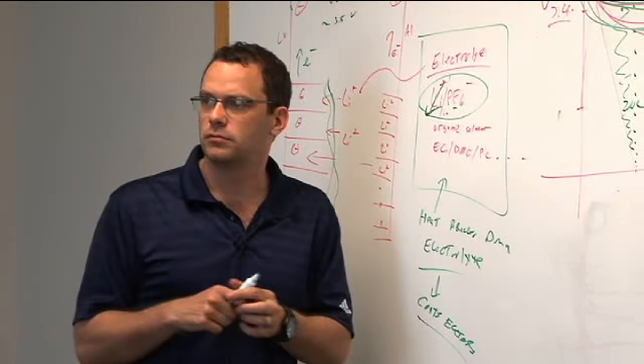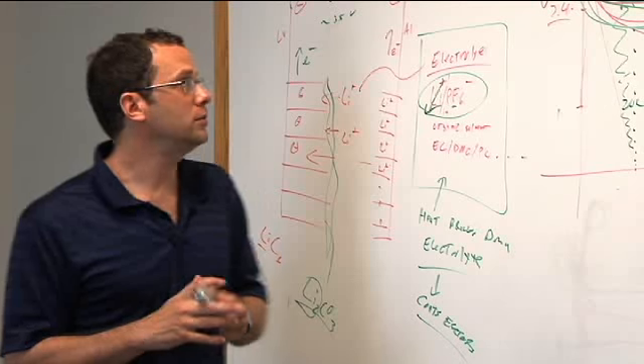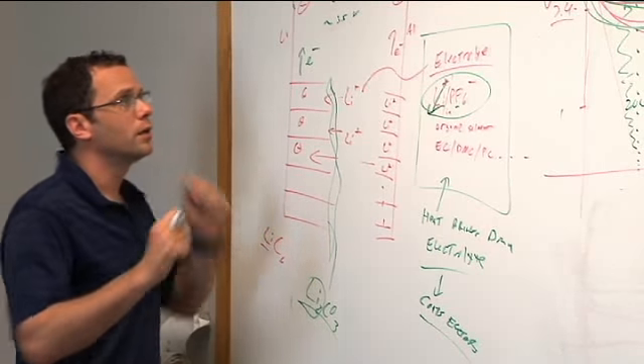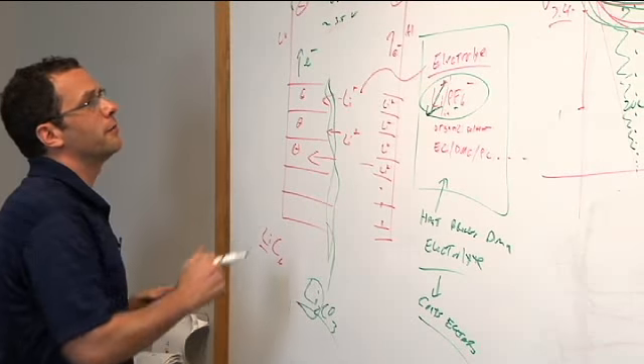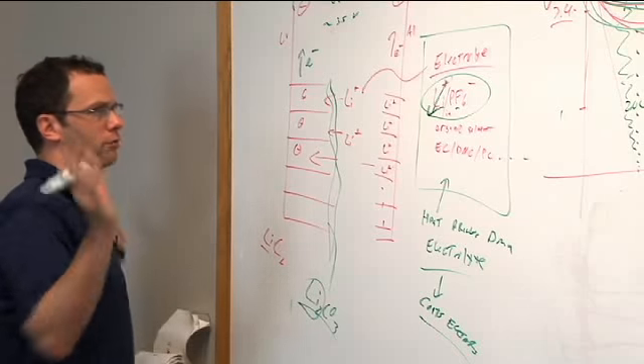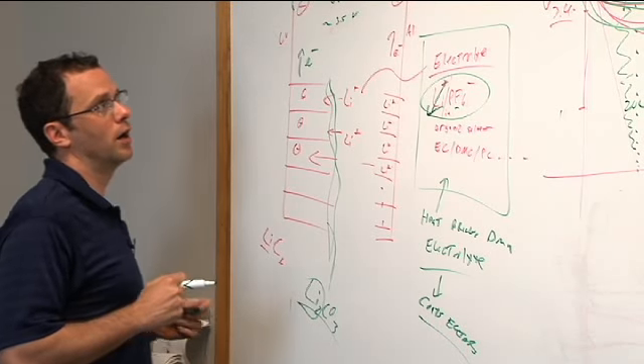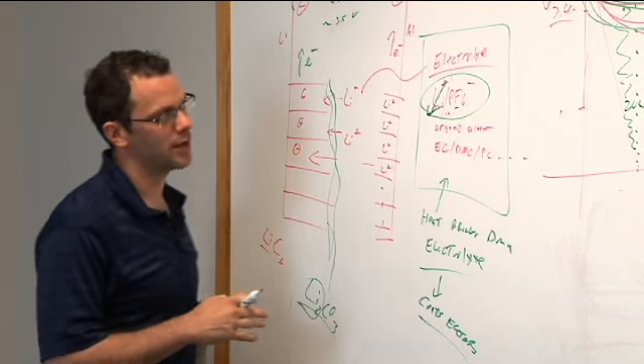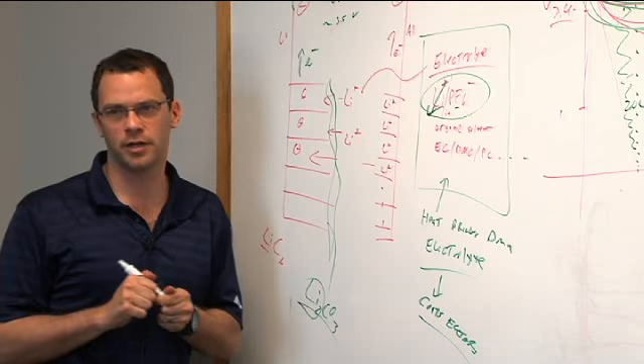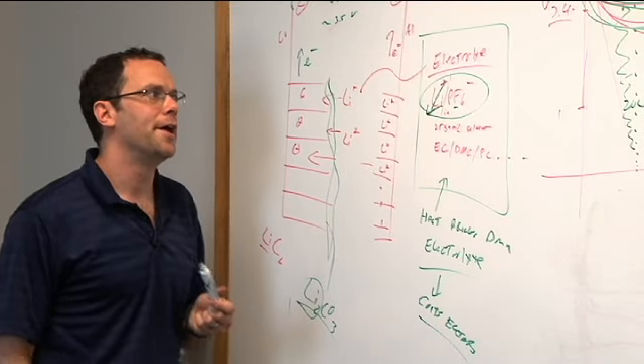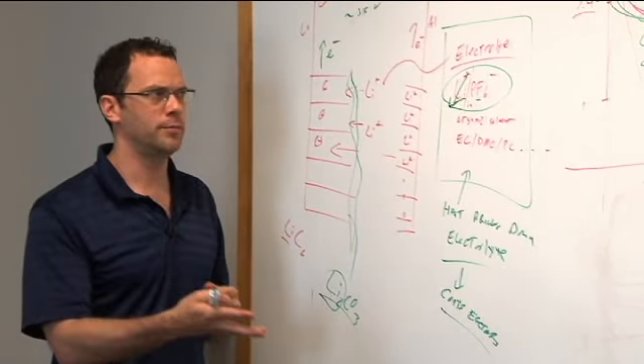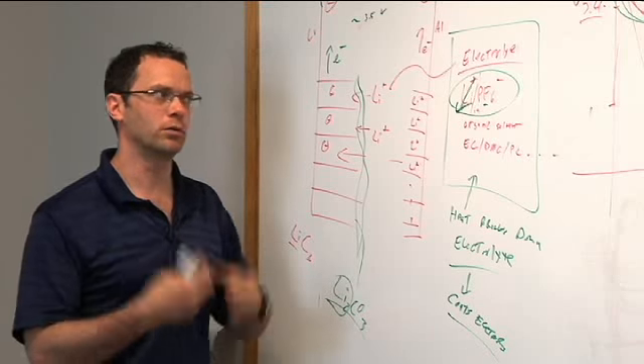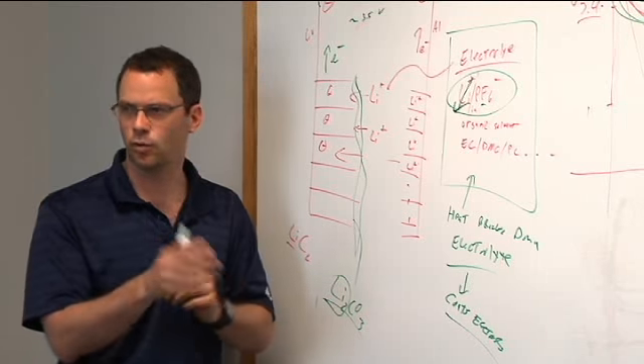What happens when we overcharge the batteries? Oh, good question. So the good news is that lithium iron phosphate cathode material can handle overcharge all day long. Much unlike lithium cobalt oxide, where you can't take all the lithium out. That's what's in your cell phone battery. If you take more than half the lithium that's resident out of it, the crystal structure is not as stable and it won't last that many cycles.